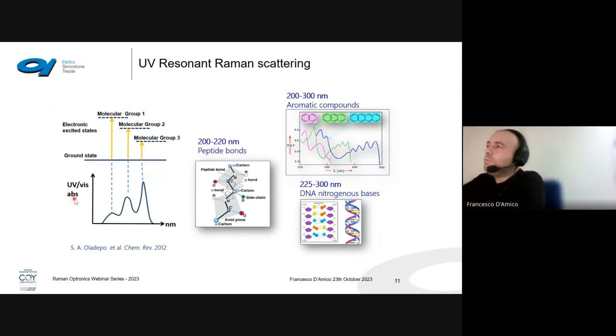In real cases, for example, we have peptide bonds of proteins that have a strong absorption between 200 and 220 nanometers. It means that if we send an incident energy in this range, we can enhance the signal from peptide bonds. The world of aromatic compounds has different absorption spectra, and each time we can select the energy to emphasize only one part of the aromatic compounds with respect to the other one. The same is done for DNA nitrogenous bases, because the absorption is in a wide region, and as we will explain better during the presentation, we can exploit the tunability in this range to investigate specific nitrogenous bases.